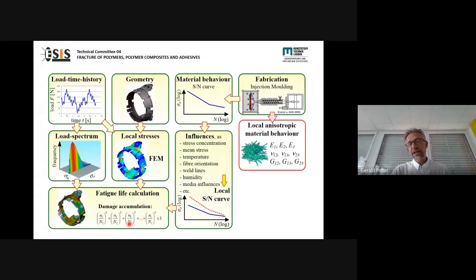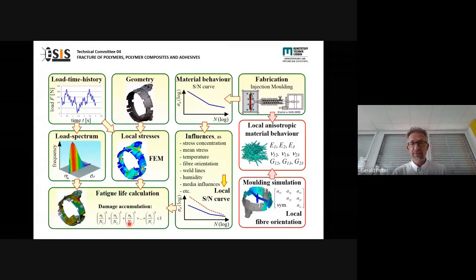And the most important aspect if you work with short fiber reinforced polymers is that, as a result of the production process, typically injection molding, you get a distribution of the fiber orientation in the component. And of course, you have to know this. You can simulate it based on molding simulations, but it's not always very accurate. But in the end, it's the basis of our calculations. You can check if the molding simulation is right based on CT analysis, so computer tomographic analysis. Based on that, you can then really do an anisotropic calculation.